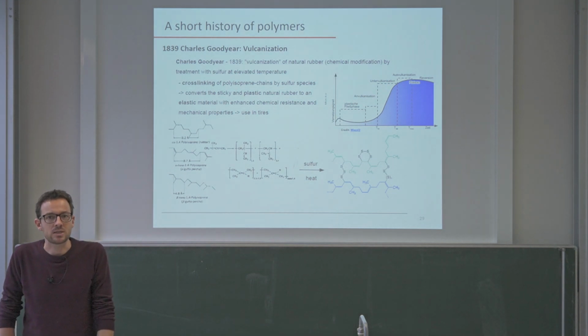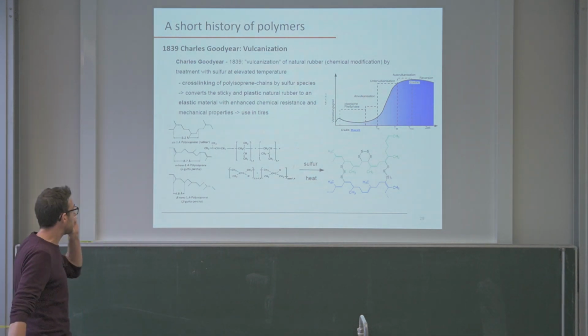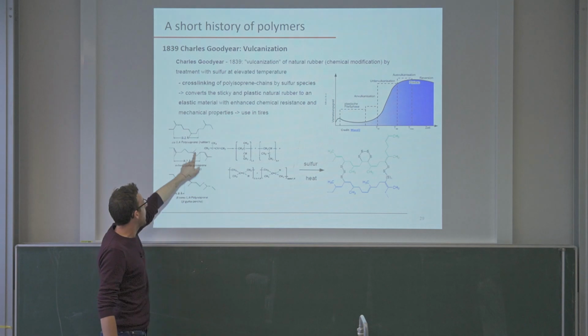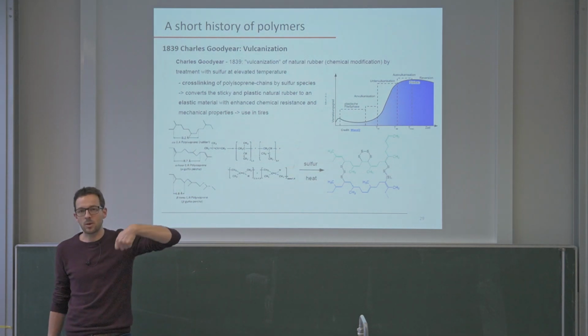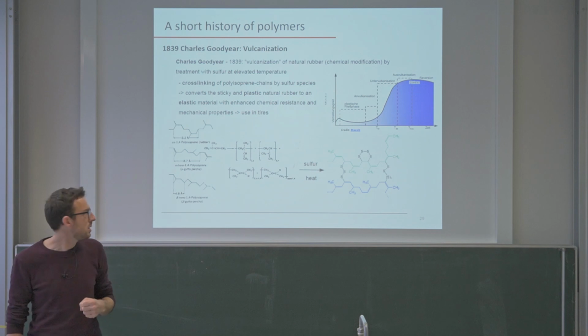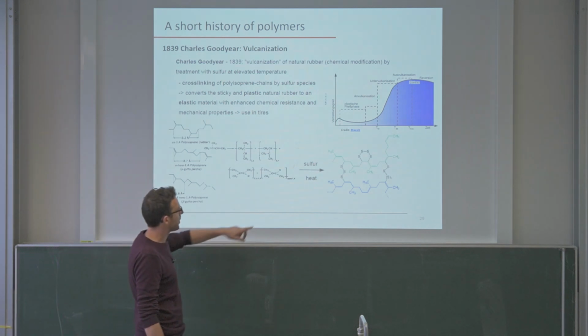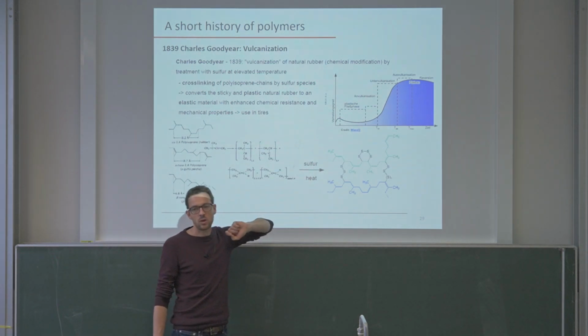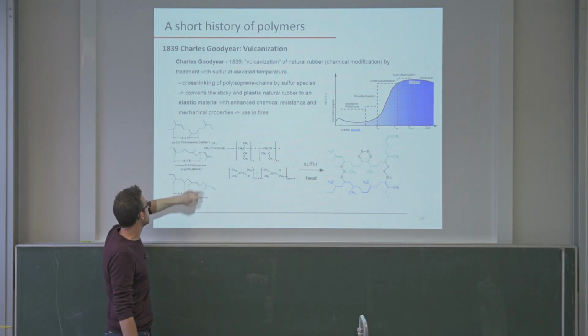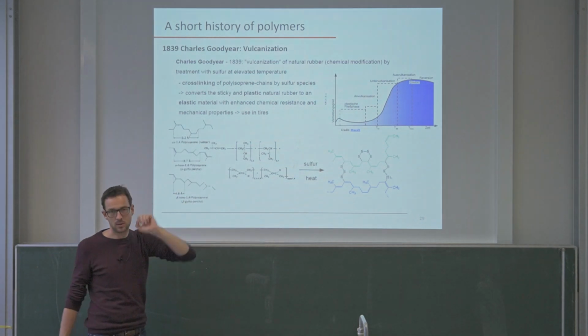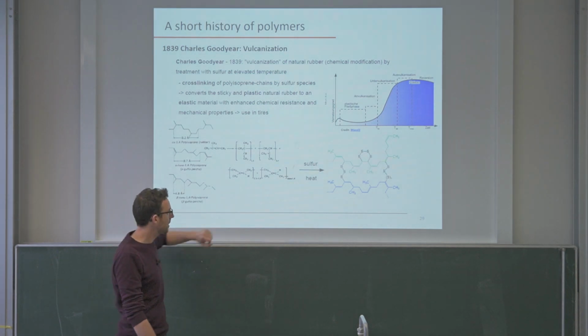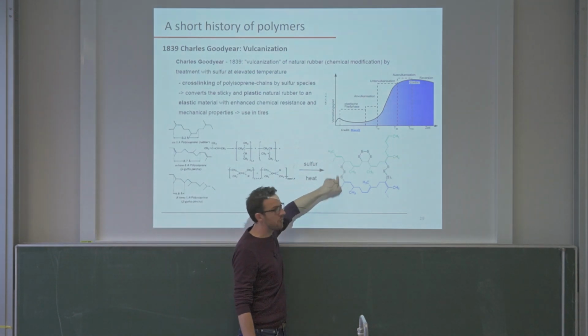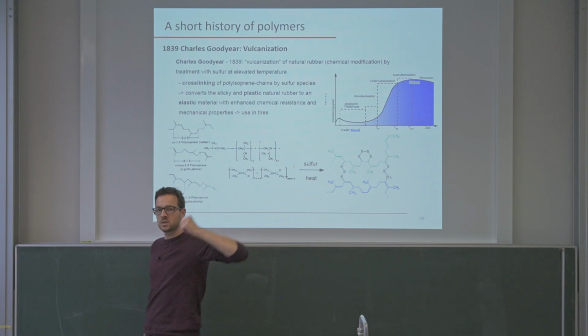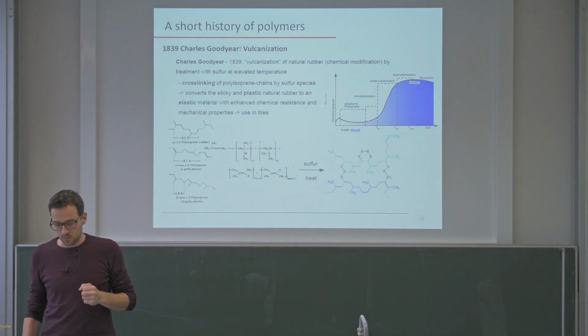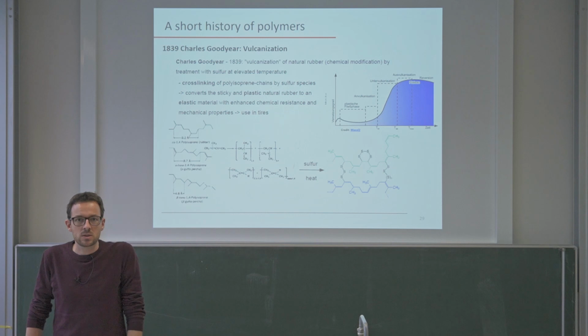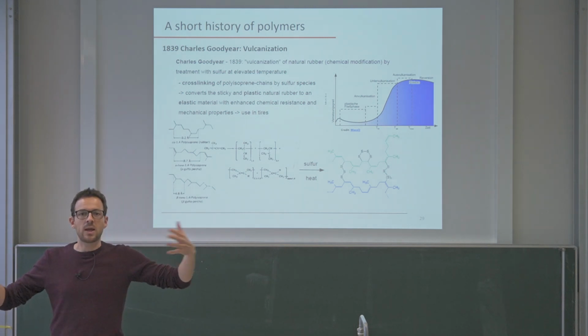Charles Goodyear discovered a process that is called vulcanization. And what he did is, so these polymers here are natural rubber. This is when you cut a rubber tree, this is what saps out. And he discovered if you boil this with sulfur, then you can cross-link these rubber materials. So you see they have double bonds here. This is again something we will go into detail a bit later. These double bonds can be connected by sulfur bridges, and this then connects the individual molecules. And as a consequence of this, you have one big molecule that cannot melt anymore.